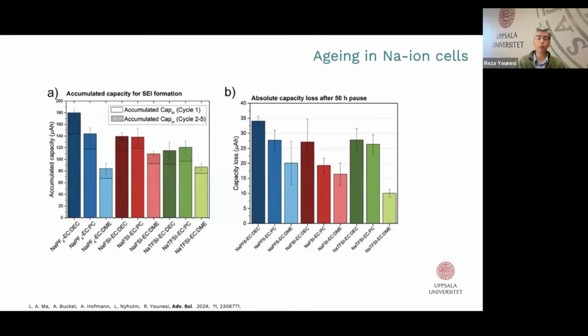So we applied this model system and the electrochemical methods I explained for different electrolyte solutions. Here we see results on three different salts, PF6, FSI, and TFSI, in three different solvent mixtures. Of course, one could use different electrolyte mixtures, but we just wanted to demonstrate this method as a possible way to characterize SEI aging in different electrolyte solutions.